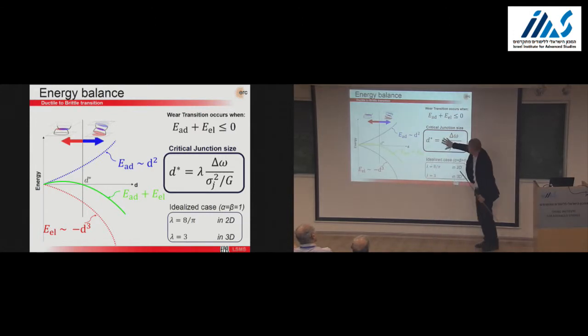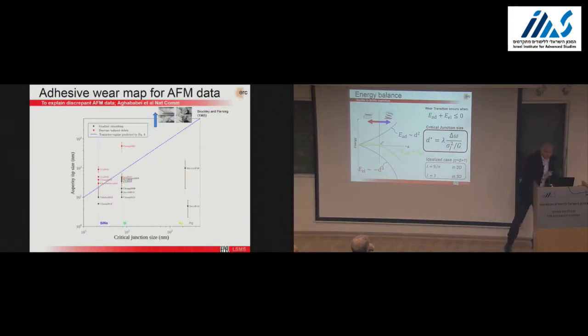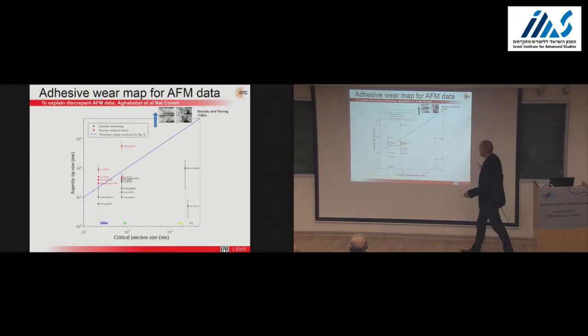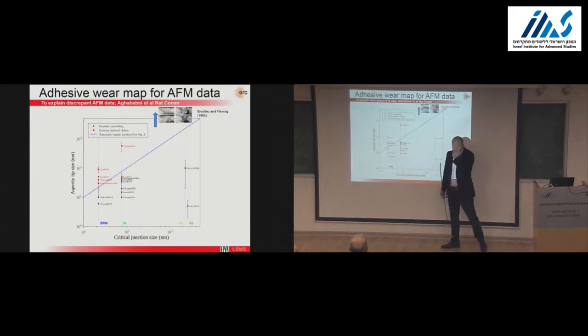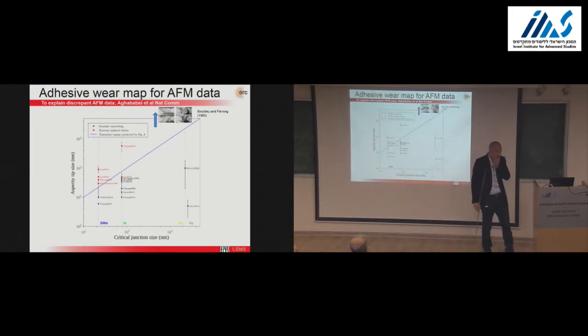So that's the expression of D star as function of material properties. It's really a material parameter. And we can compare this to a geometrical parameter, which is the size of a contact. OK, so that's what we've done with the AFM data we could put our hands onto.